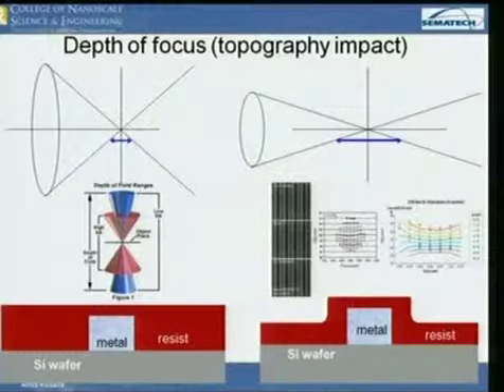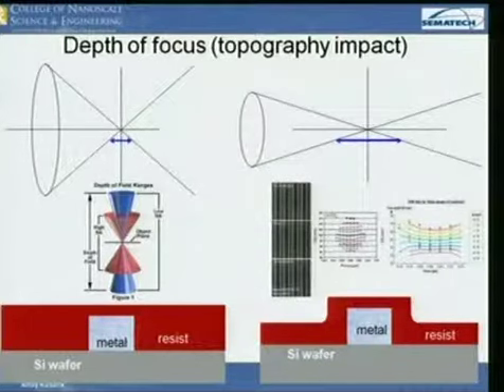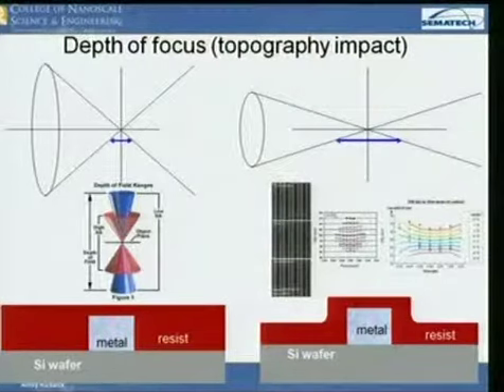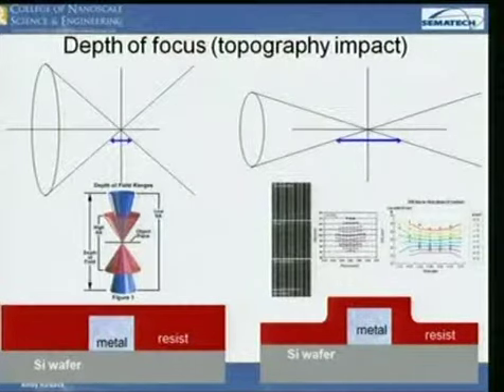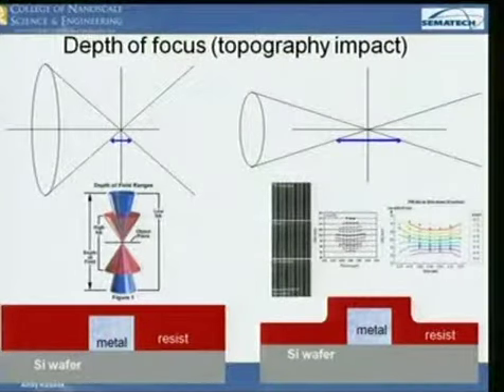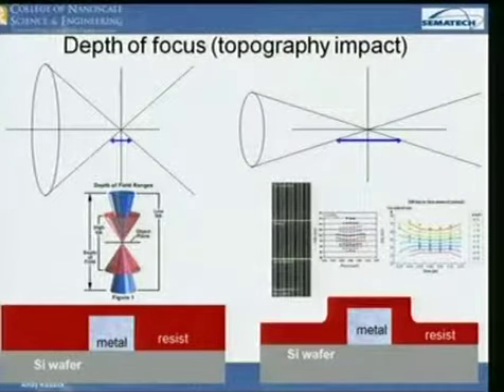And what you can see is we get this, what we call spider plot. And what that shows is if I'm printing a 25 nanometer, or let's say 30 nanometer line here, that's the blue line, as I change my focus, my feature starts changing. And that's why this blue line does a little drop there. There's no data there. That's kind of a terrible extrapolation. But in any case, that's kind of what happens. The CD changes as I change my focus and my exposure energy. This is called the focus exposure matrix. We do that because we want to find what we call the isofocal point. The isofocal point would be this flat line. Because what we want is we want to be able to expose any layer and not have to worry about focus. So we want the isofocal point. Now the problems that we encounter are, and you can see this is ideal.